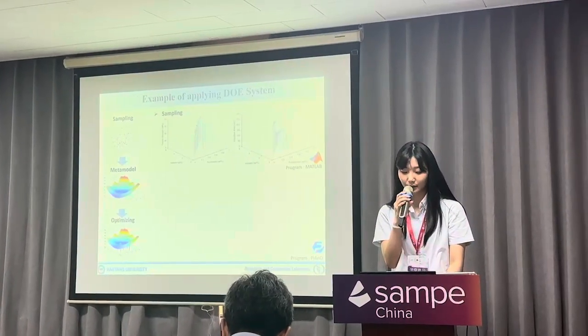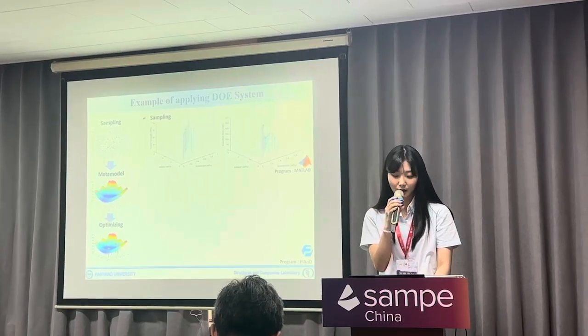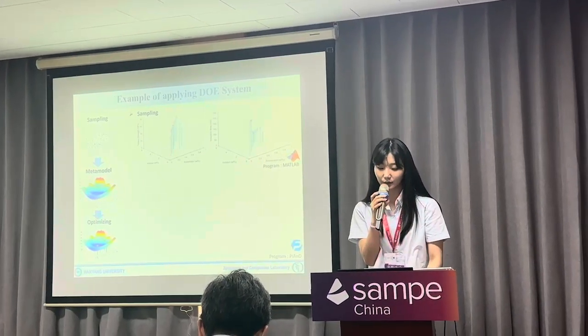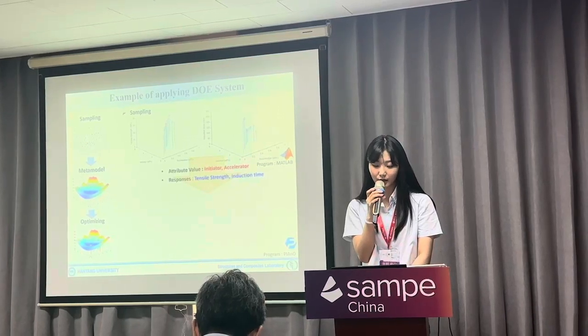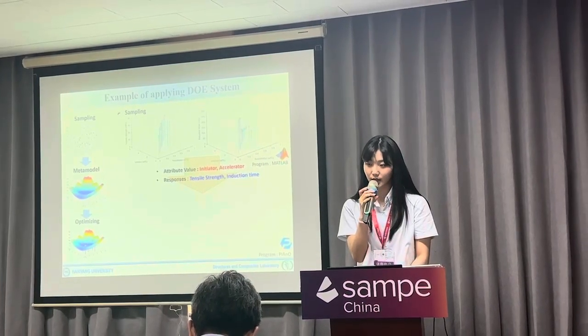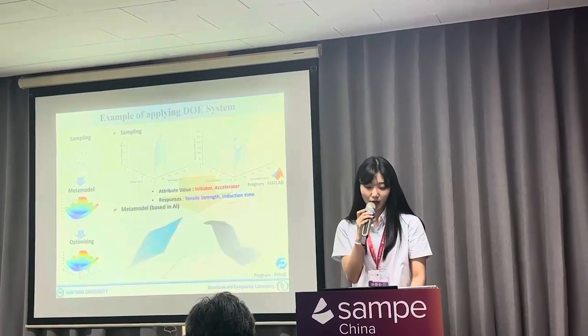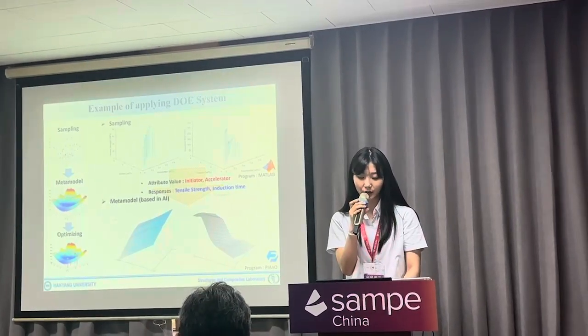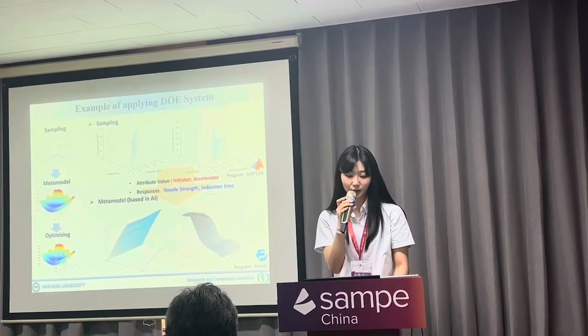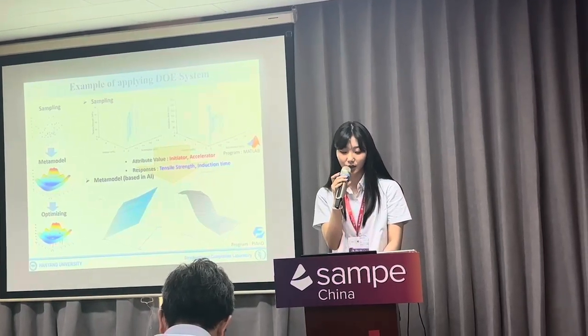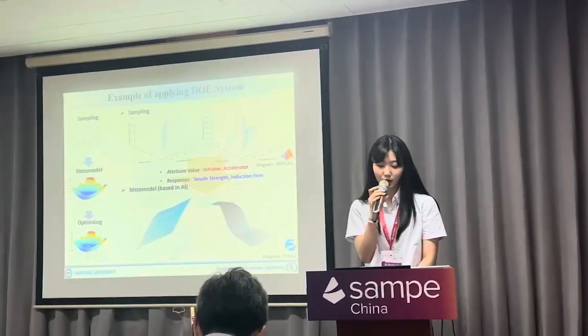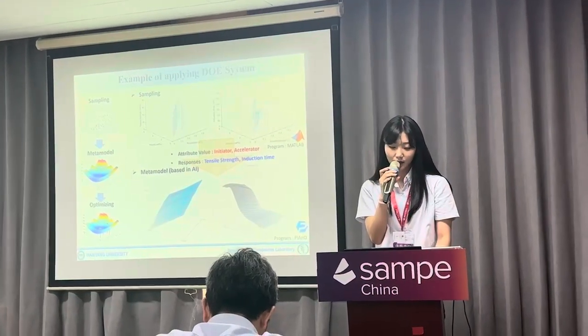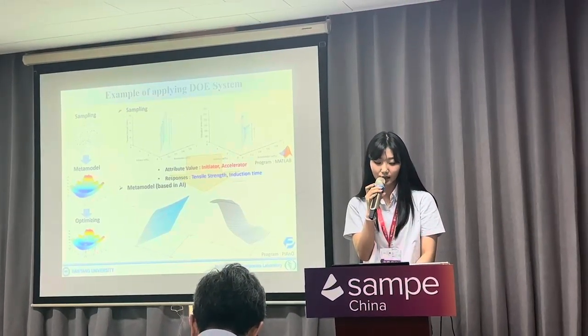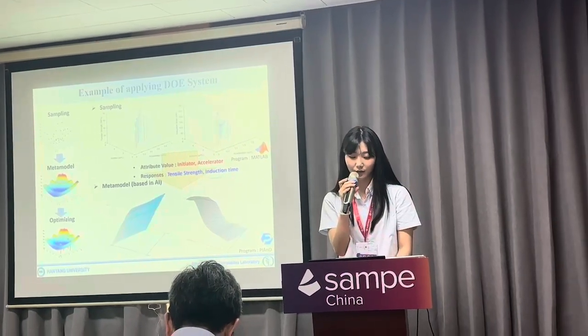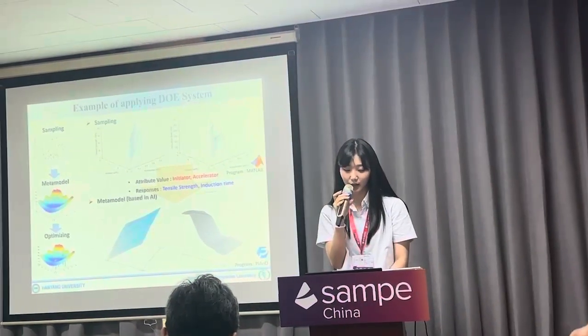Now I'll introduce one example that I used for optimizing the resin system. First, I made a sample of experiments that I conducted before. Here, I used initiator and accelerator as attribute values. Responses were tensile strength and induction time. After sampling, I made a meta model using PIANO, which is an optimal design program developed in Korea. This is very effective in conducting optimal design using DOE methodology. Using this meta model, it is possible to obtain expected values for points that have not been tested, based on existing experiment points. And also, we can identify the correlation between each attribute value and responses.